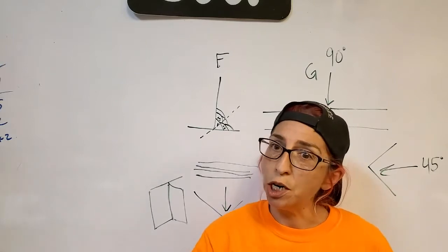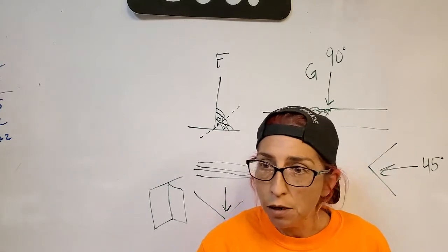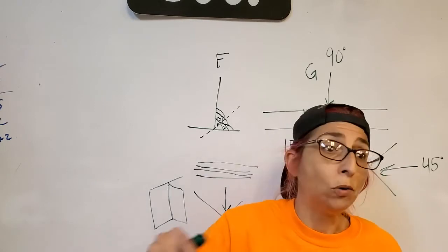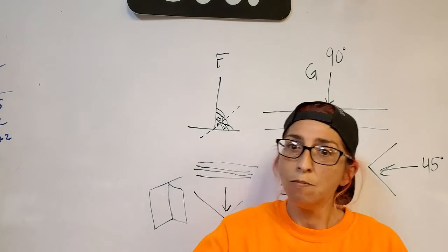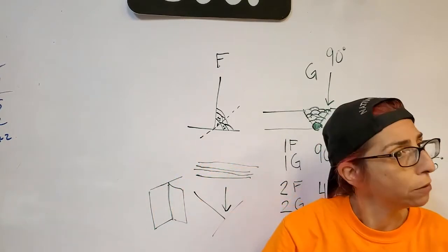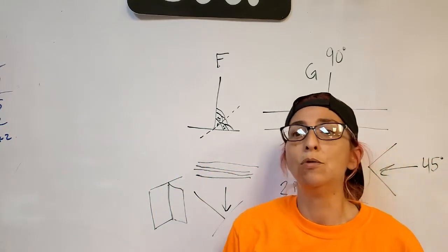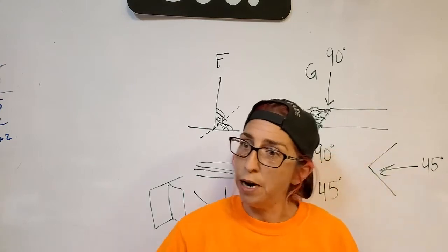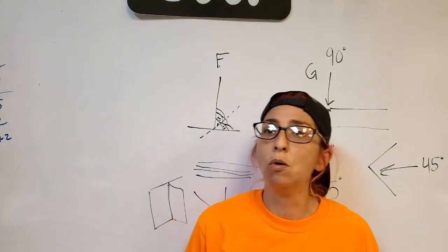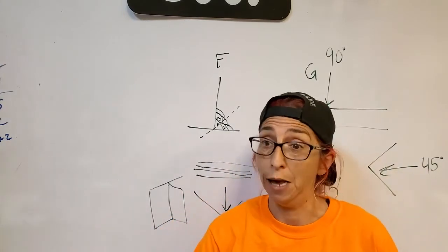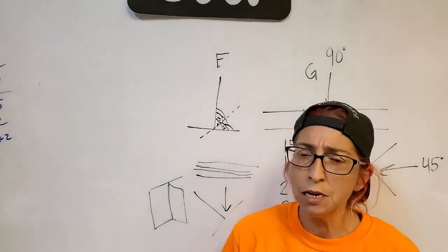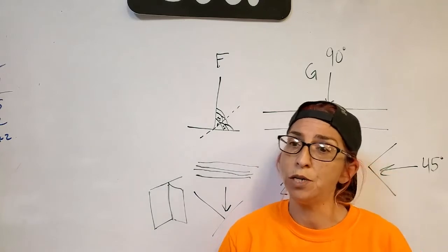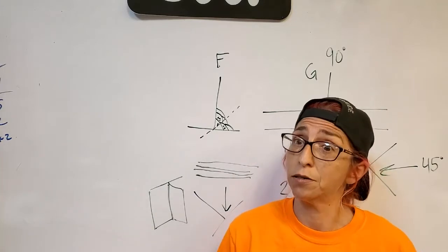And usually with stick or anything that's followed with slag, you usually don't go vertical down. You're more likely to have slag inclusions because the slag rolls over your bead. Unless you have the proper technique, you do not want to go downhill with anything that has slag. And not only that, it really wasn't meant for that. It's meant for deeper penetration, especially when we're talking about stick or flux.